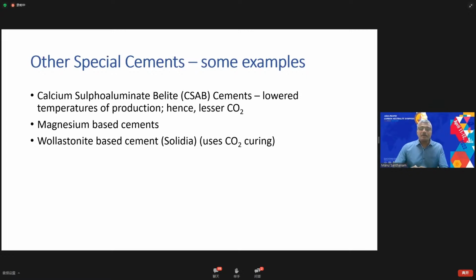There are cements formulated based on CO2 curing, carbon dioxide curing. One of these is called Solidia, a wollastonite-based cement. The idea is that when you mix it with water, you cure it in a carbon dioxide environment, the CO2 is captured, and you convert the active phases into calcium carbonate and calcium silicate, leading to a sequestration of CO2 in your systems.